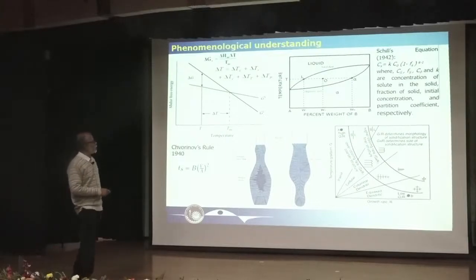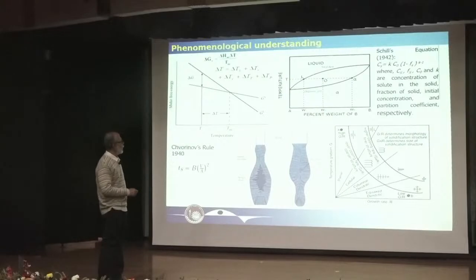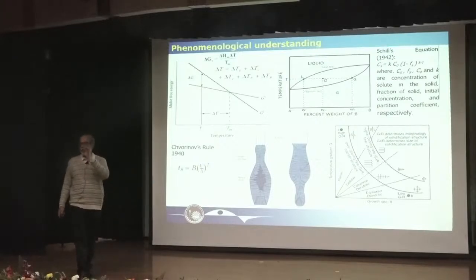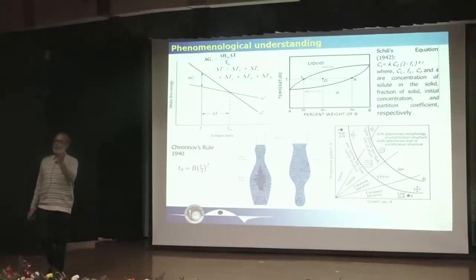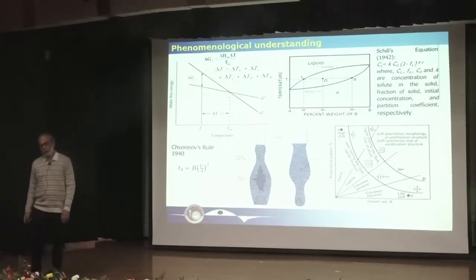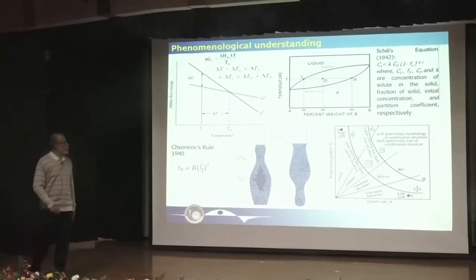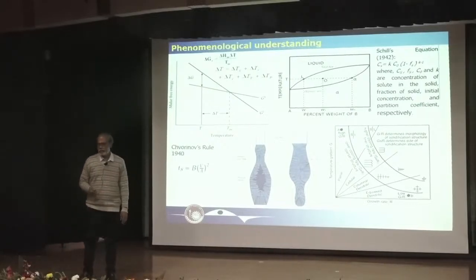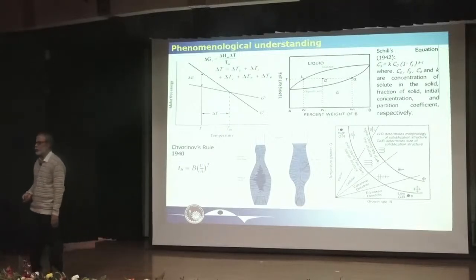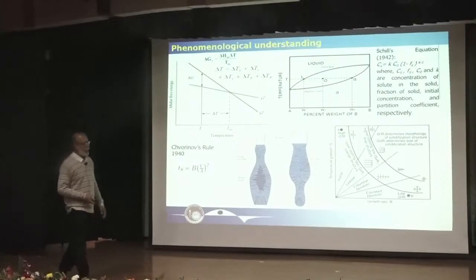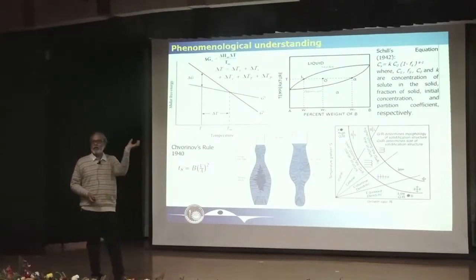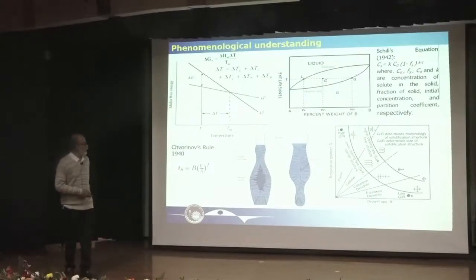So Scheil proposed an equation of non-equilibrium partitioning, where Cs is the concentration of solute in the solid, K is the partitioning coefficient, C0 is the average composition, and f is the fraction transformed. So it is partitioning in terms of fraction transformed. That is, during the course of the process, you could interpret the partitioning behavior of solute across the liquid-solid interface. So this was basically used in CALPHAD. Even today we are using CALPHAD as a very useful software for assessment of phase transformation, and Scheil's equation provided the incorporation of non-equilibrium features in the CALPHAD process.